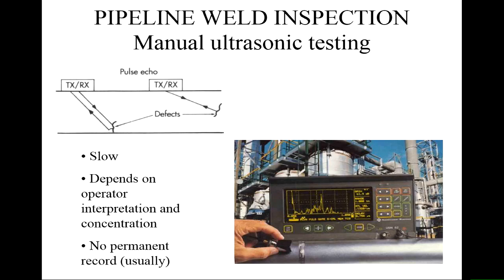transmitted sound, and by looking at the time of flight you can then detect different types of defect, different types of reflections. So here's an example. This probe, you can see the probe's at an angle, so we're actually scanning this weld because it's coming in at an angle like you can see at the top there, and depending on the distance from that weld you can go through the thickness of the system, and you get a complex picture like this where you'll get a main peak here. This is probably the peak that's associated with reflection off the back surface, and then there might be some other noisy peaks there as well, and then there are some other defects in here. So you get a bit of a mess, and again a skilled interpreter can tell you, oh, there must be a defect, lack of fusion or something like that.